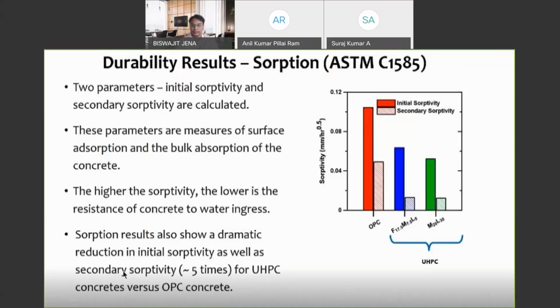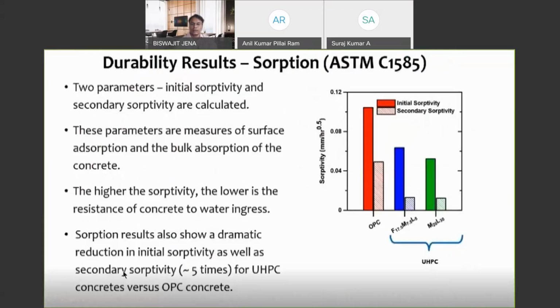Okay, so finally we go for a few notes on durability. Here we have tested the sorptivity, or water transport, similar to the relationship regarding durability that is also tested for in the RCPT test. You can measure the initial sorptivity, which is the water intake immediately after you put it in for 6 hours, and then the long term sorptivity that you measure for 10 to 14 days.